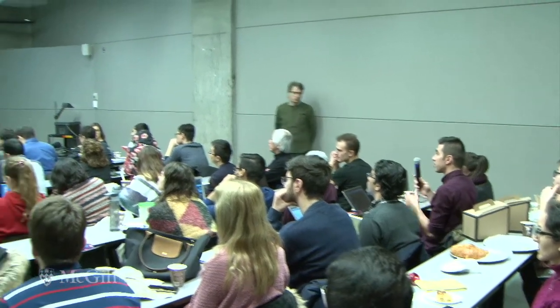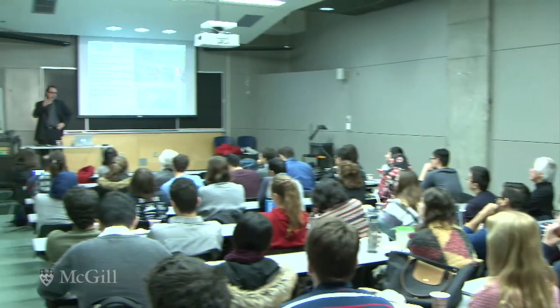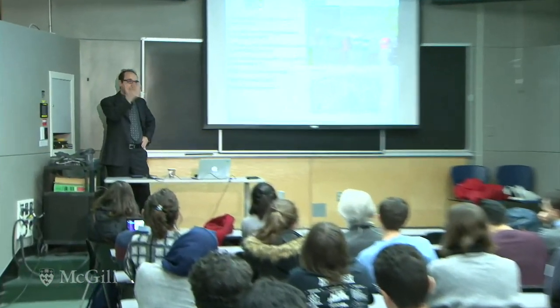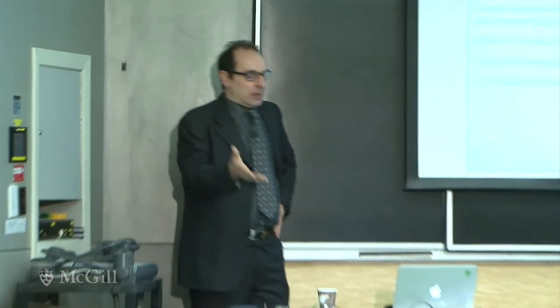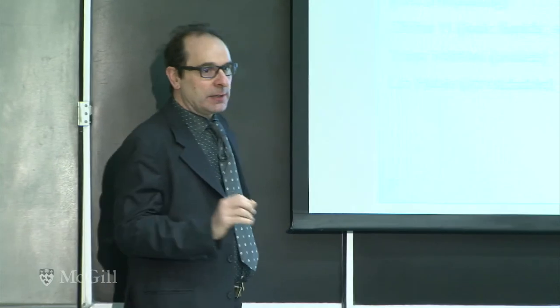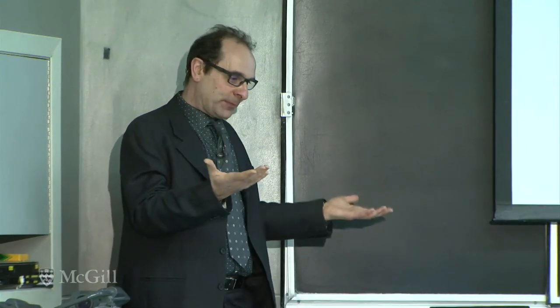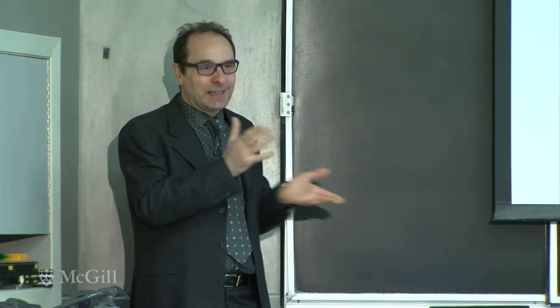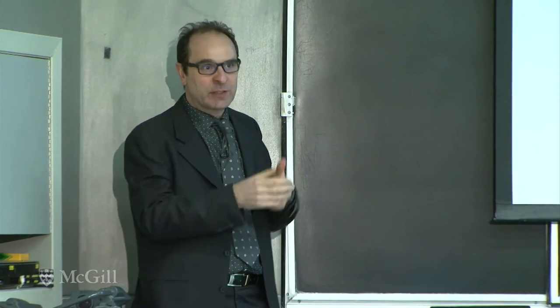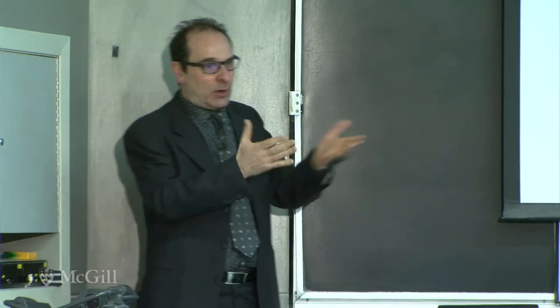OK, first question, it's something we are trying. So to achieve the cut by patterning, we are not successful yet, because I think we have to reach a compromise between the thickness and the size of the cut. Then there is another thing. When you cut the material by lithography, by patterning, you usually use oxygen plasma, which changes the chemistry of the material. So the process might not be the same.